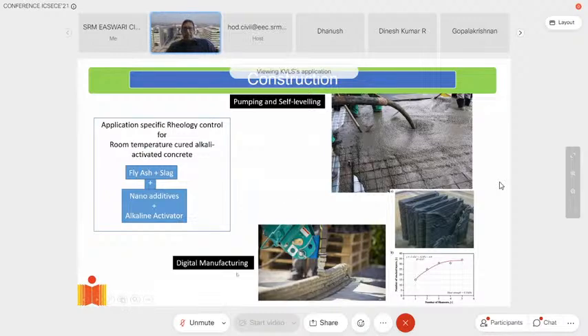On the other extreme, where I'm getting into digital manufacturing, I need concrete to flow under pressure, and I should be able to stack layers, basically put one layer on top of another and build an entire structure. It's the same concrete. I still achieve the same strength from the two. It's just by adjusting the composition that I'm able to vary the performance of the concrete in the fresh state and achieve the performance requirement that I need in the fresh state.